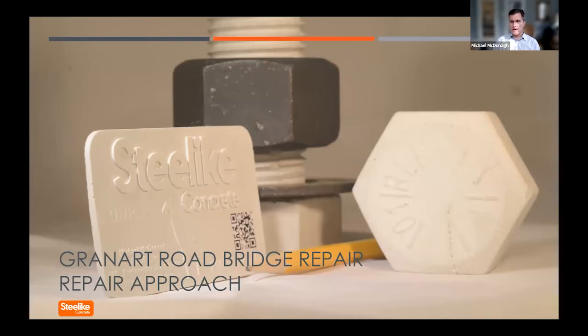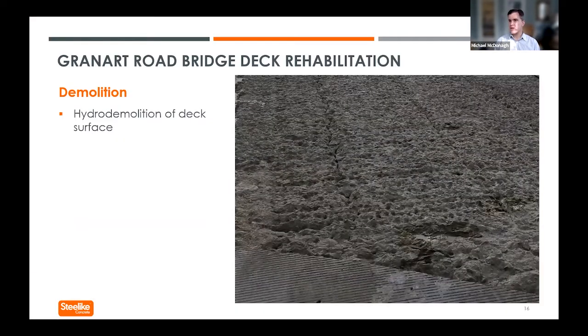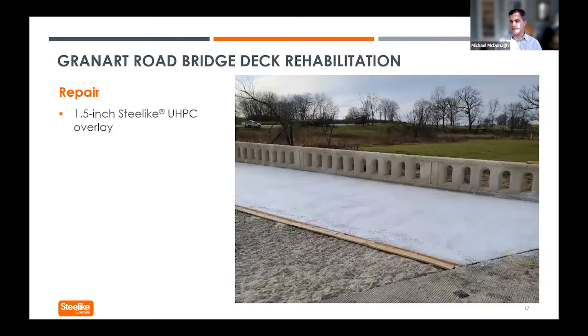Now, the Granart Road Bridge, which had the distressed deck. The first step to rehabilitate the deck was to hydrodemolition the top surface of the deck to remove dirt and soiled concrete, and create a roughened surface, essentially a clean roughened surface. And then quite simply put down 1.5 inches of UHPC.